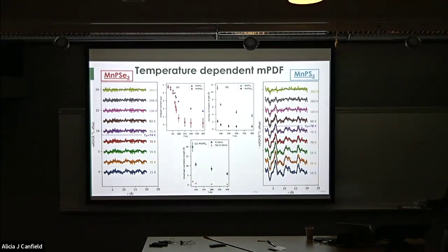For S3, in the plane, this is where all the correlation is. Just at the transition you have around 20 angstrom, and then it drops off to just a bit above 5 angstrom. Out of the plane you really have very limited correlation, showing that this is a good approximation for a two-dimensional material. You try the same thing for Se3 and it just blows up, with huge error bars. The bulk is not behaving like a material yet.